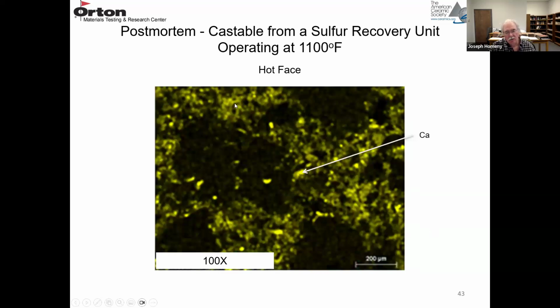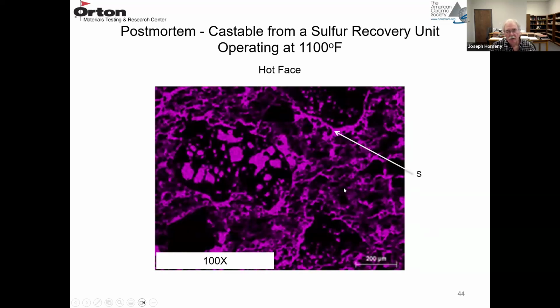And then the yellow is in the matrix. That's the calcium from the calcium aluminate cement. And then the purple is the sulfur that is diffused into the material. It's primarily diffusing through the matrix, but it also diffuses into the open pores in these coarse aggregates that are quite porous. So these have to be open porosity on these coarse aggregates.